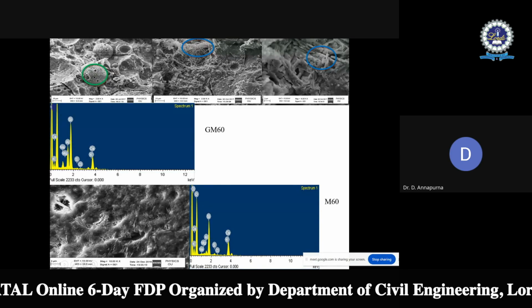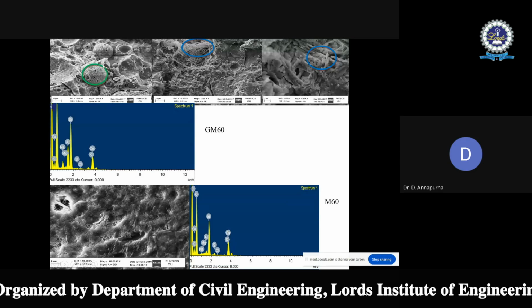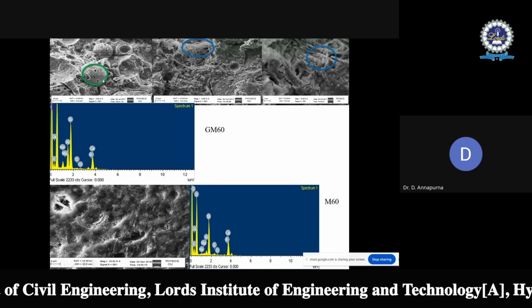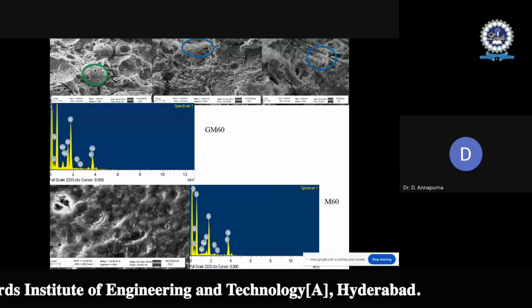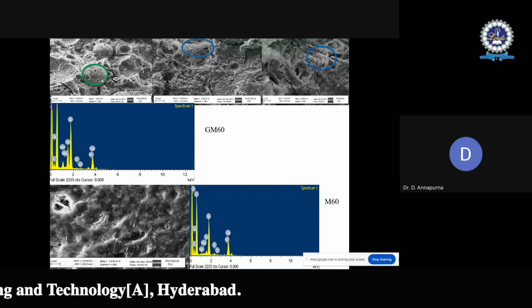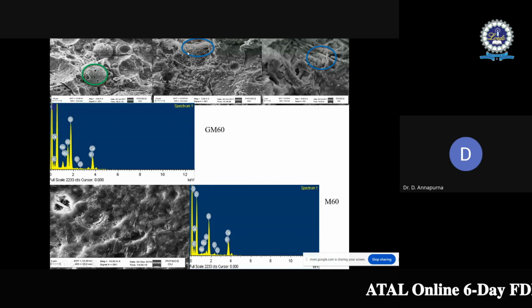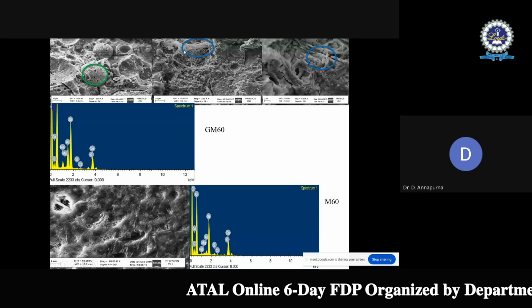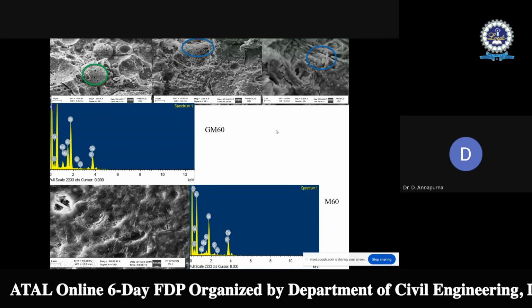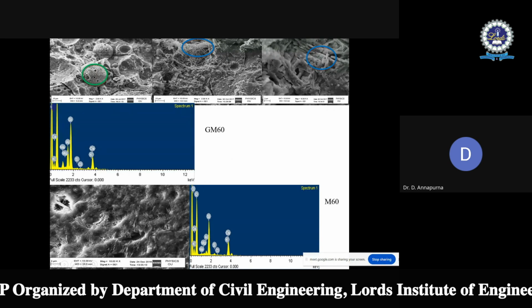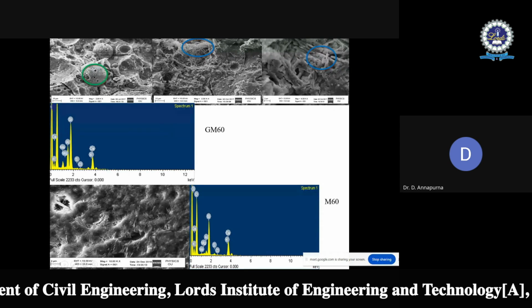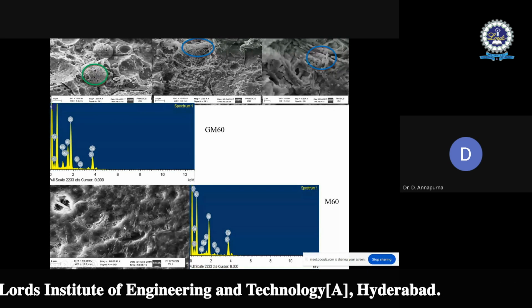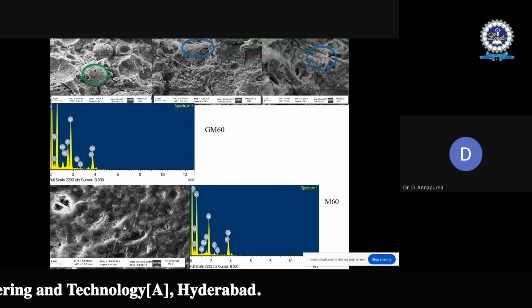GM60, we can see decomposition of the geopolymer product on top of the fly ash particles. If we look at the decomposition of this geopolymer product, it is visualized. At the same time, in some parts the formation of aggregate and gypsum can be seen. And in case of normal, conventional concrete, the complete decomposition of calcium silicate hydrate is seen through the sulfate